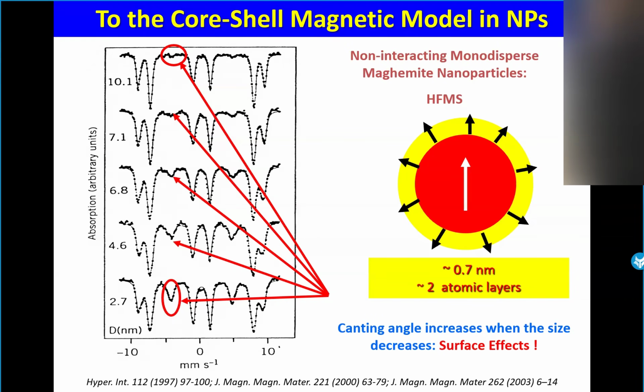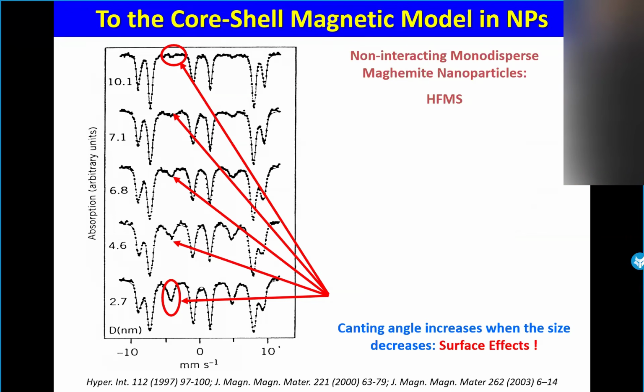So it was possible to describe it by means of a ferrimagnetic core with a random distribution of magnetic moments at the surface. And it was possible to estimate the magnetic surface at about 0.7 nanometers, let's say about 2 atomic layers. This result is very important because Nader will explain this afternoon that, of course, these two layers are very important at the interface.